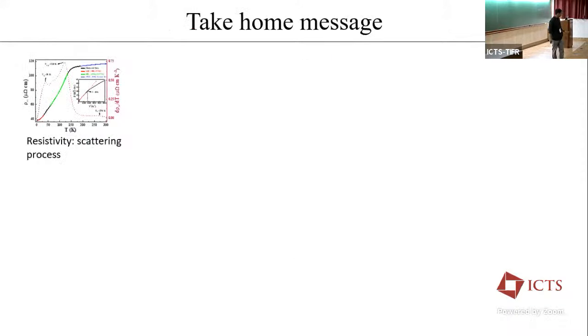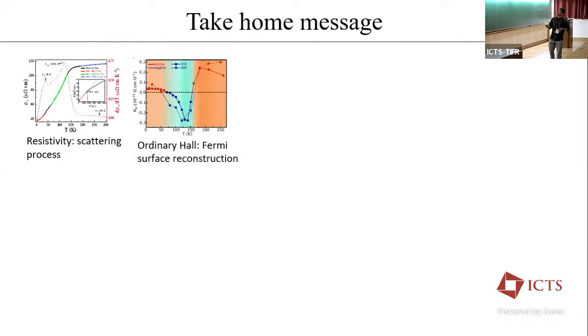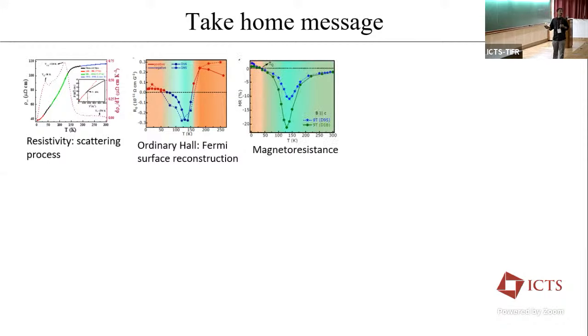So with this, I think I'm on time, so I'll just summarize my talk. So first thing what you observe, that resistivity, we did a detailed understanding about the scattering process, what is happening, and we observe an unusual ordinary Hall effect, where we see Fermi surface reconstruction. There are two transitions from the Hall we can determine. Then we also see in magnetoresistance two transitions, like one here and one here, that is in line with your previous observation.